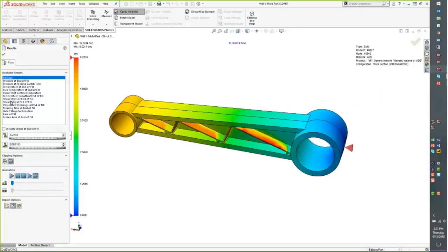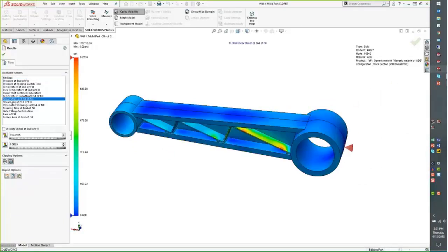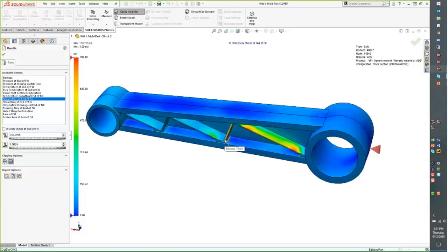And if we look through here, we can see things like shear stress at the end of fill. We can see that there's a lot of shear on these ribs, and that's because we're just not at a point where we can push that forward and push that part through. So if the flow front comes through with a low shear, like we see at this top flange and the bottom flange, it means it flowed through there pretty easily. Here we see a high shear stress. It's indicating that we had a problem filling that.